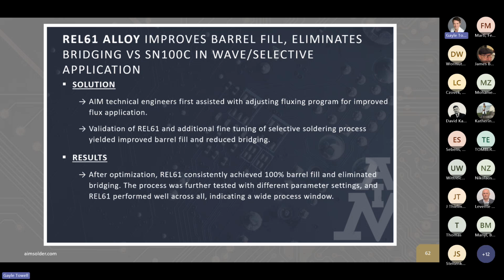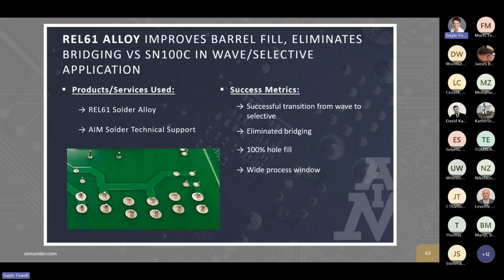After dialing everything in, REL61 consistently achieved 100% barrel fill and eliminated the problems with bridging. And the process was further tested with different parameters. REL61 performed well across all different settings, which also indicated a nice wide process window. So they were able to successfully transition from a wave soldering to a selective soldering application. And again, they eliminated the bridging problem, had very good hole fill, and proved a nice wide process window.